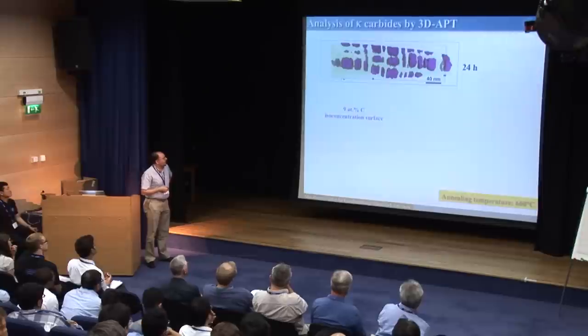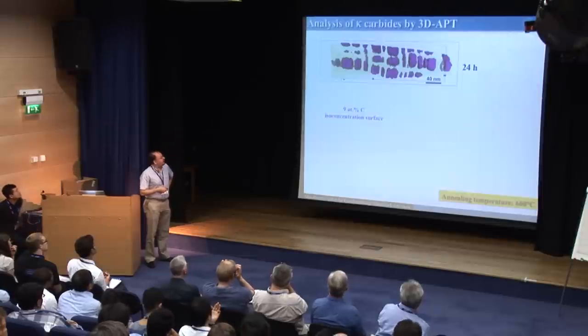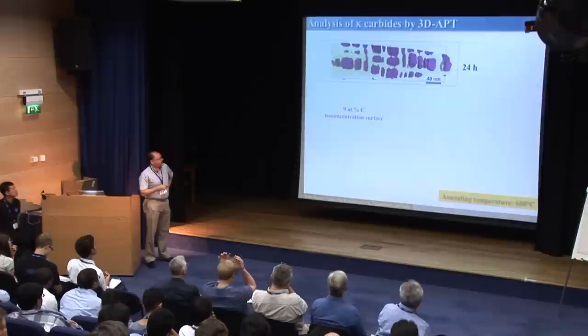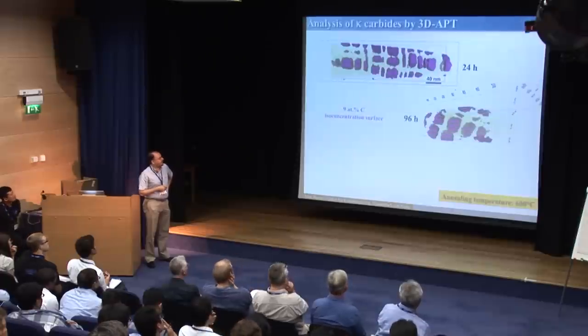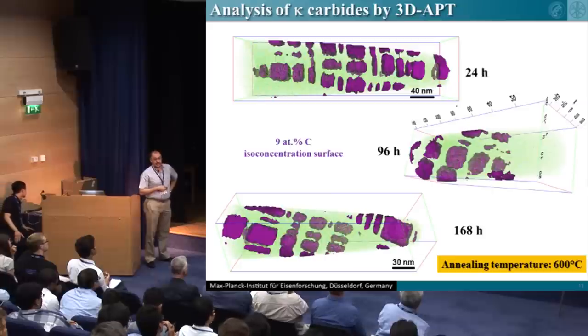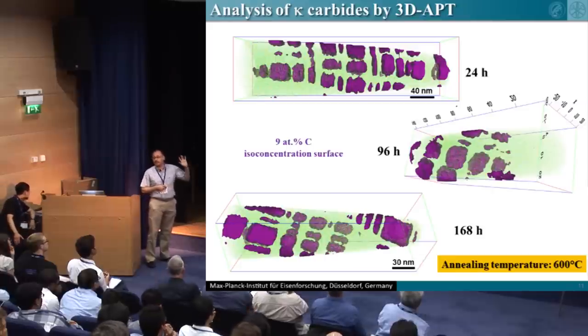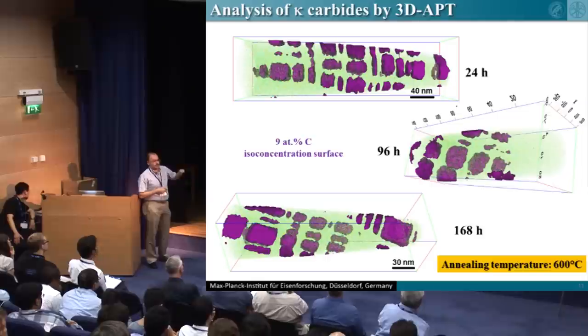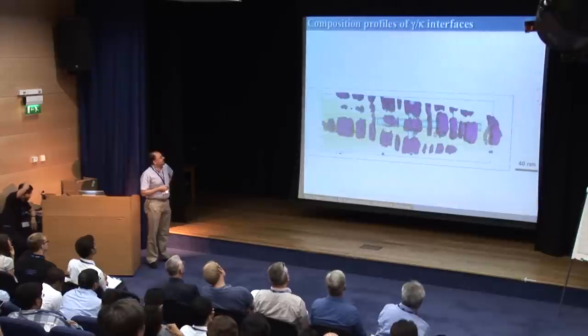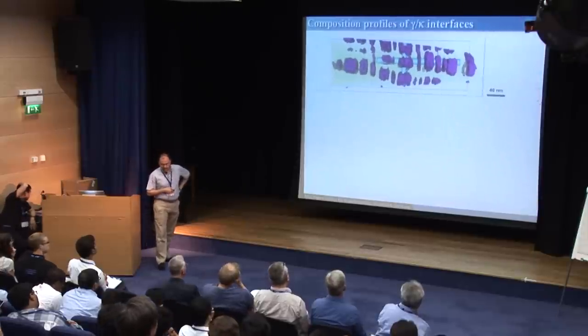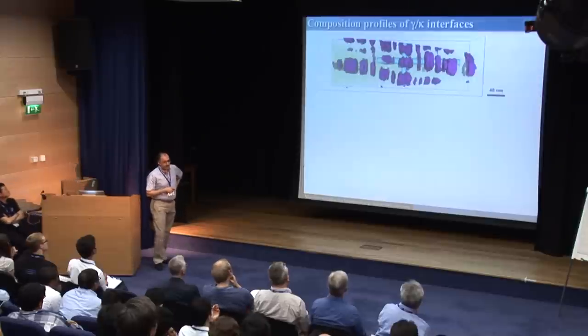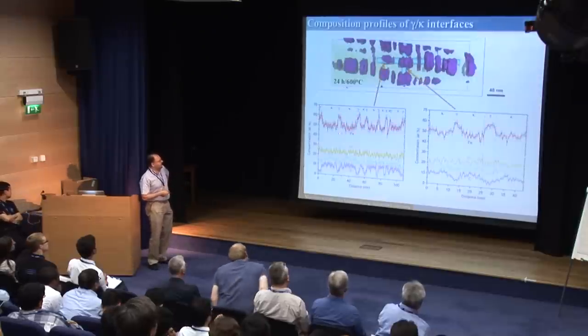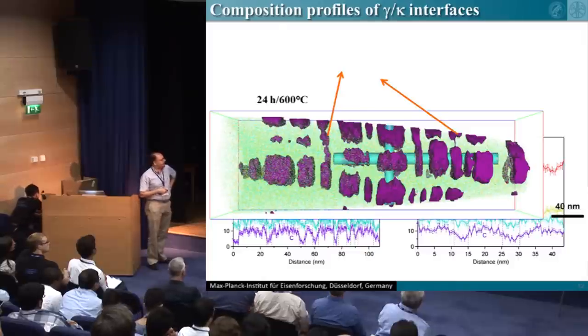We are also characterizing kappa carbides in the austenitic matrix by 3D APT. These are reconstructed isoconcentration surfaces. We are using 9 atomic percent in this presentation at different annealing times. You can see that it's very nice for APT analysis because in one needle we have several particles, so we can nicely identify the partitioning behavior. If one takes a look at the 1D concentration profiles, they look like this one, for instance.